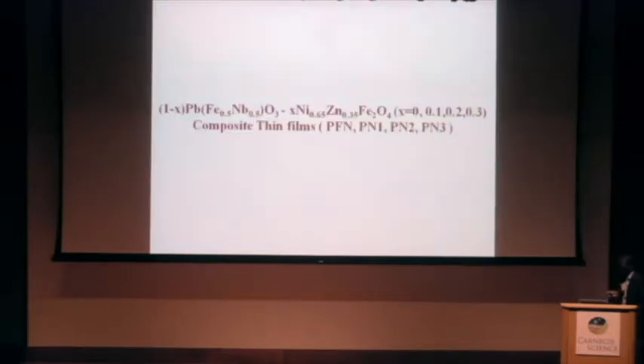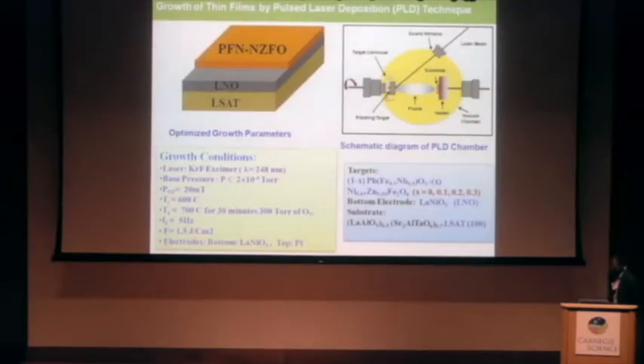So these are our (1-x) PFN-x NZFO composites, and we have synthesized 10%, 20%, and 30% compositions, which can be abbreviated as PN1, PN2, and PN3 throughout the talk. We have synthesized single-layer thin films, because previously we synthesized some multilayer films, but due to substrate clamping, we could not get such high magnetoelectric couplings. That's why we plan to grow single-layer thin films with a PFN and NZFO composite.